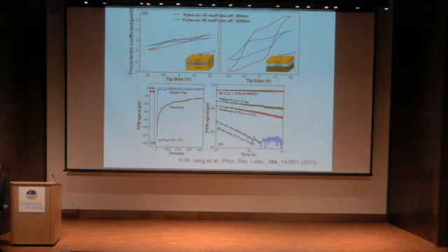Many years ago, we had been working on this strain-free dielectric thin film, strontium titanate. At the time, we compared this with strained strontium titanate on neodymium gallate, which has a very strong ferroelectric behavior. However, we still see some kind of ferroelectric behavior for a very short period of time in the strain-free strontium titanate.